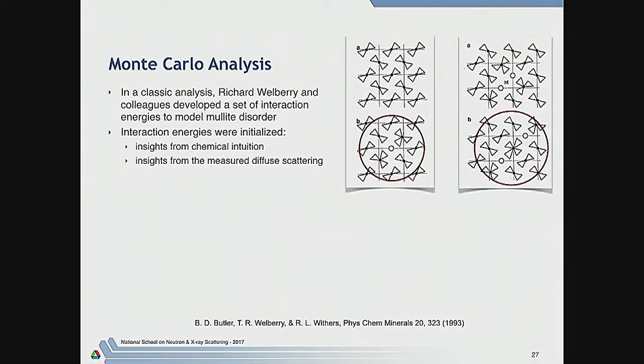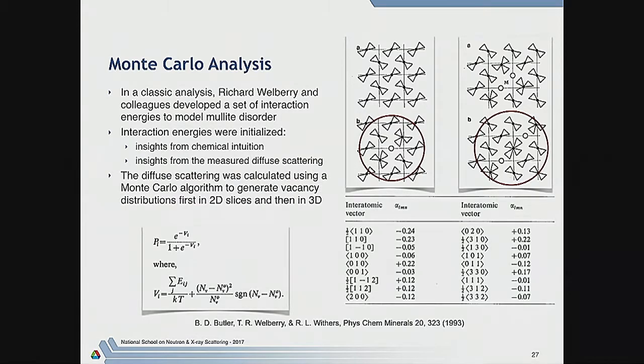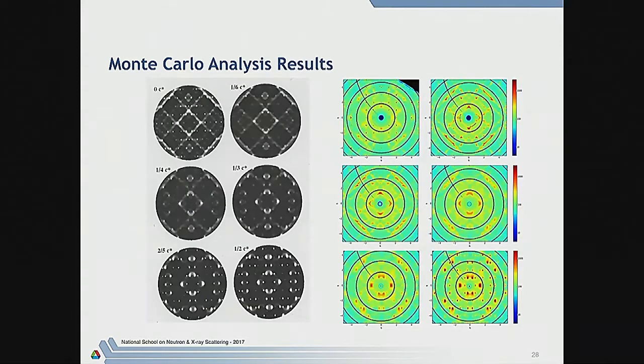So he basically came up with an energy landscape and produced a whole set of parameters which he was then able to optimize against the data to produce these Warren-Cowley parameters, saying what is the probability that if you have a vacancy here that there'll be another vacancy at other equivalent sites. And as you can see, he did a beautiful job. But this takes quite a lot of time, okay, and also brilliance.